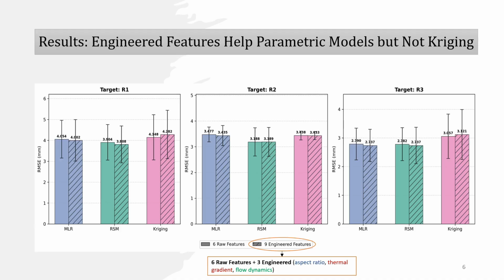This is the central result of the presentation. The plot shows root mean square error values for R1, R2, and R3. Lower root mean square error means better prediction. For MLR and RSM, adding the engineered features generally gives a small improvement, especially for R1 and R3. The improvement is not dramatic, but is consistent enough to suggest that the physics-informed features are adding useful information. For R2, the difference is much smaller, which means that arc height remains difficult to predict.